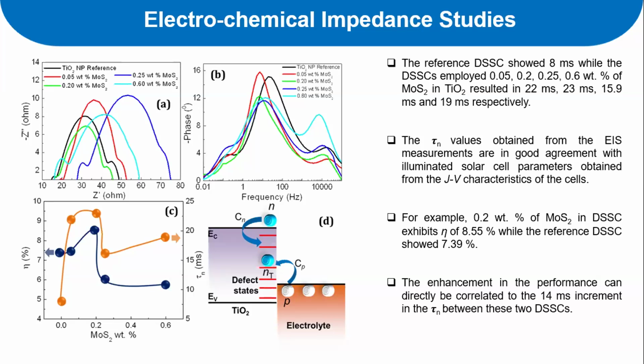Basically, the 2D layer semiconductors are getting coated on top of the titanium dioxide, and the band structure is being aligned very well. The conduction band of the moly sulfide is aligned below the conduction band of the electron acceptor titanium dioxide. So once we have that optical absorption, it efficiently increases. In that particular case, the charge carrier lifetime is significantly increased. And if we keep increasing the quantity of the 2D layer semiconductor in the electron acceptor titanium dioxide, then the charge carrier lifetime falls down. It decreases. The reason is it got agglomerated and it doesn't help in terms of charge transport.